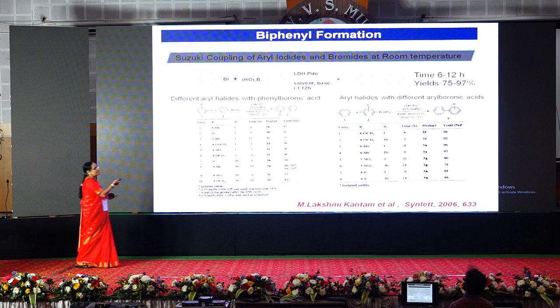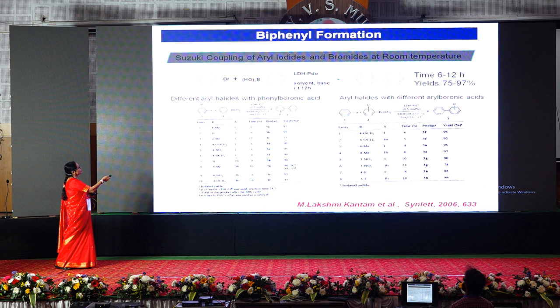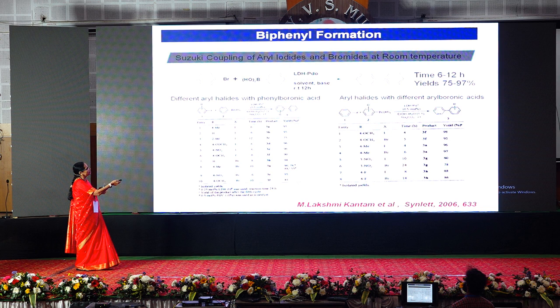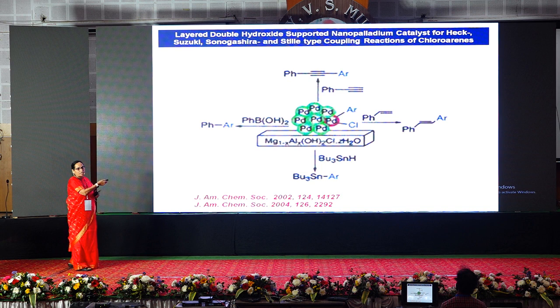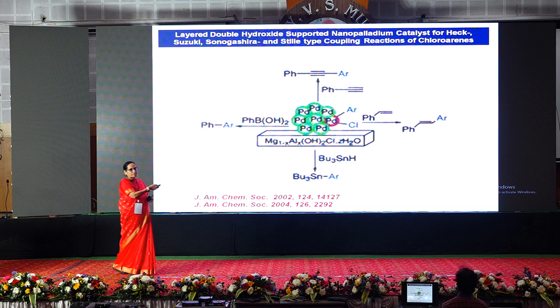And similarly, the same catalyst, palladium on hydrotalcite, works for this reaction. The important thing is it works at room temperature, and in 12 hours it gives the biphenyl derivatives. And you can see it can also do the Stille coupling, Sonogashira coupling, any type of reaction you can do with this simple catalyst.